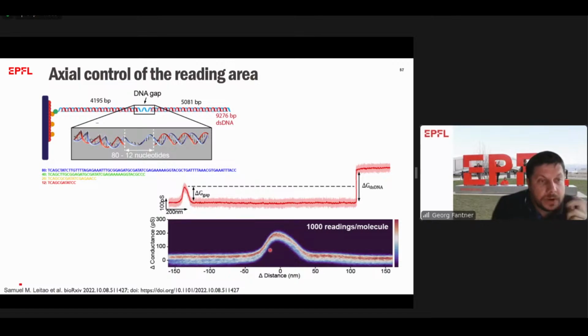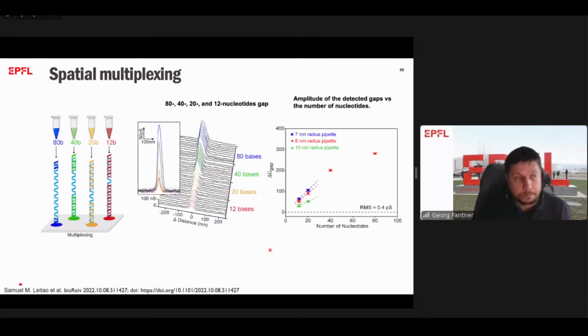but we didn't quite know yet how high. So we decided to make multiple of these test molecules, where we had molecules that had 80 base gaps, 40, 20, and 12. And this here are really the raw data curves. And you see we have a very strong signal at 80 base gaps, 40, 20, and even down to 12 base gaps, we still have a lot of signal to noise left.